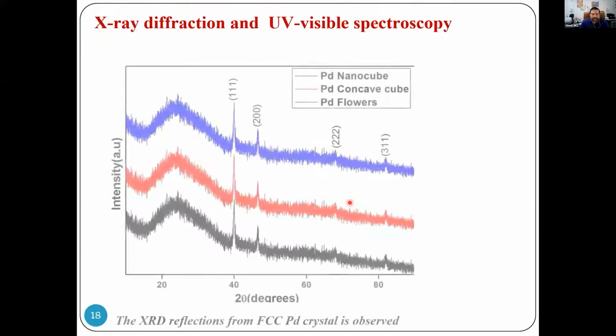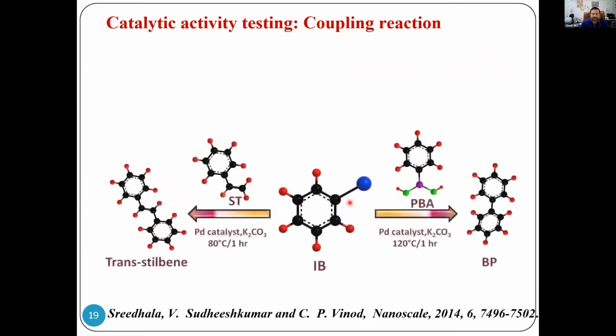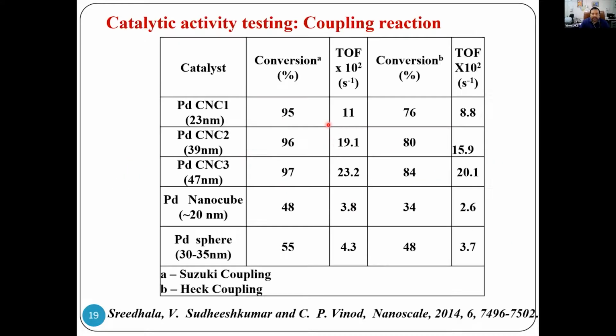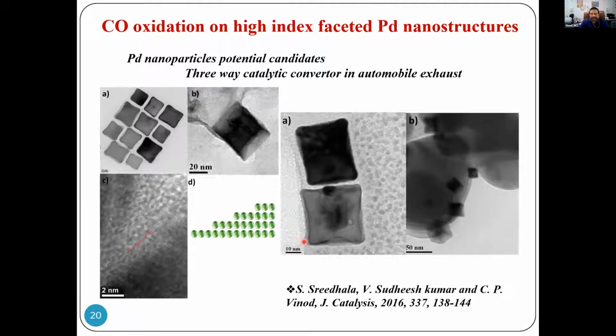Now I skip all these things, and then I will show you the catalytic activity. For example, if you run a coupling reaction with this, you clearly see the difference between a low index faceted surface and a high index faceted surface. So for example, we have a concave nanocube with 23 nanometers and 39 nanometers. It shows very high conversion, 95 to 96%. Even 97% in the case of 47 nanometers, whereas a palladium nanocube, which is a low index faceted surface, gives only 48%, whereas a normal palladium sphere of the same size as the concave nanocube gives only 55%. So again, it clearly demonstrates the facet dependency or the structure sensitivity of these reactions.